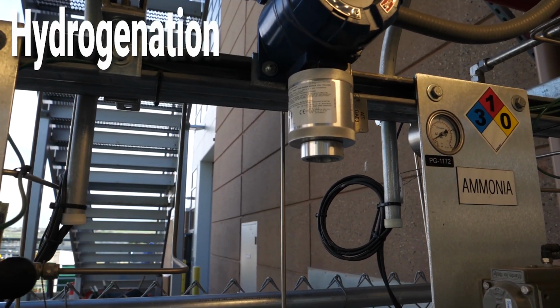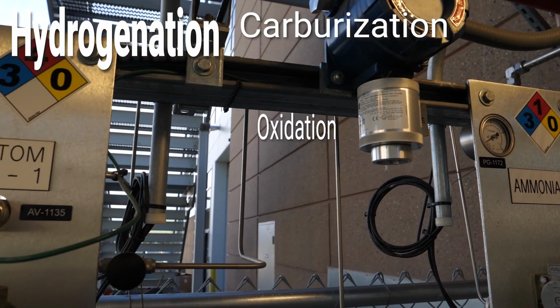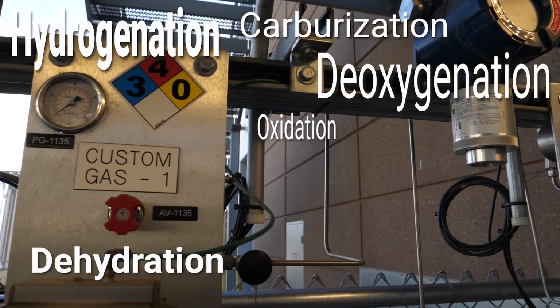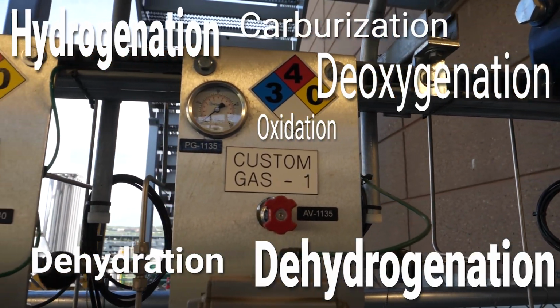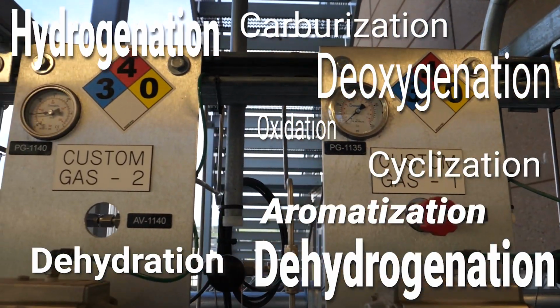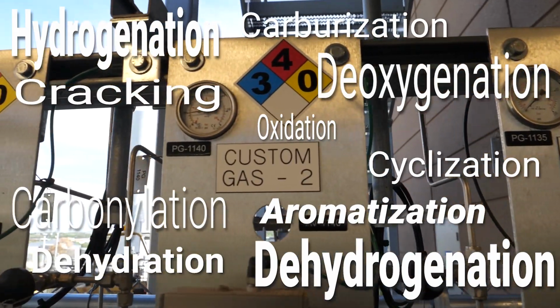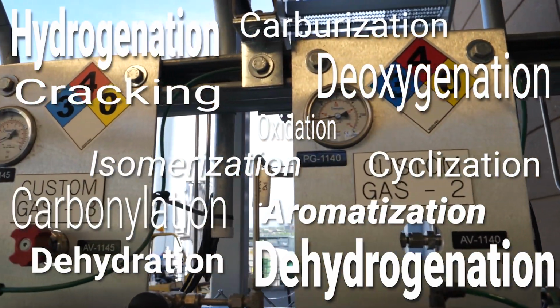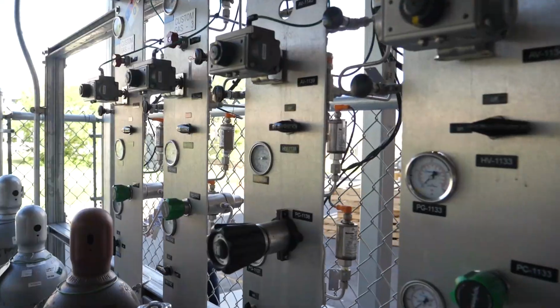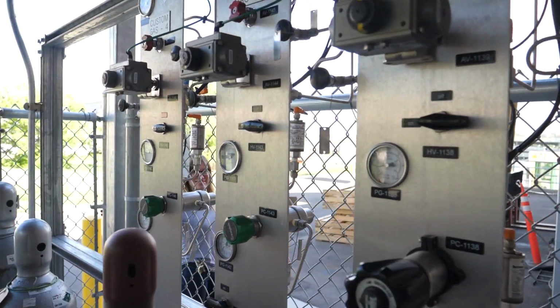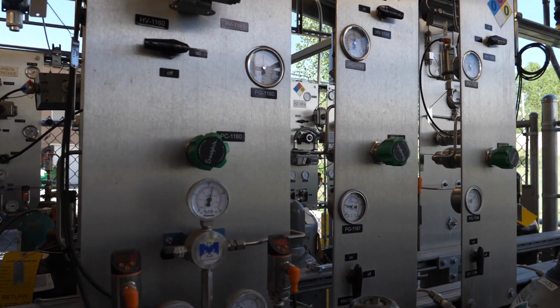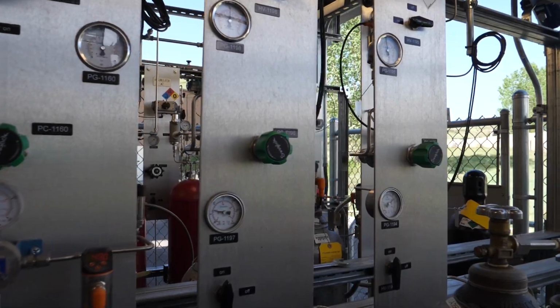We can perform hydrogenation, oxidation, carburization, deoxygenation, dehydration, dehydrogenation, cyclization, aromatization, cracking, carbonylation, and isomerization reactions of gases and liquids using solid catalyst materials at pressures up to 100 atmospheres and temperatures up to 1000 C.